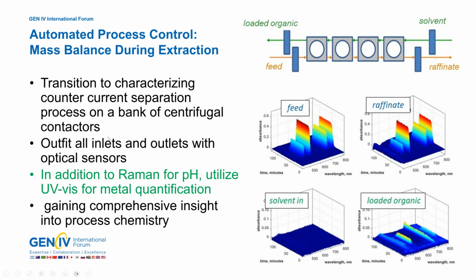In this automated process control, we also performed a mass balance during the extraction. I've mentioned that the citric acid feed we're using is used in TALSPEAK. TALSPEAK is a process for the separation of lanthanides from actinides. We have a citric acid feed, and we're monitoring the UV-vis for metal quantification in this particular example. In the feed, in this case, it's a simulant.